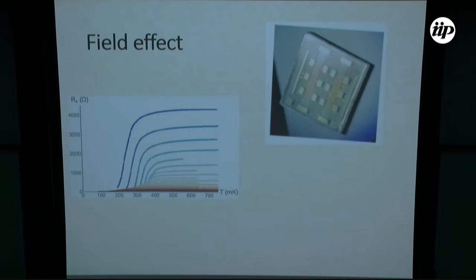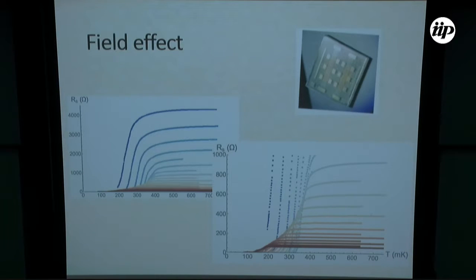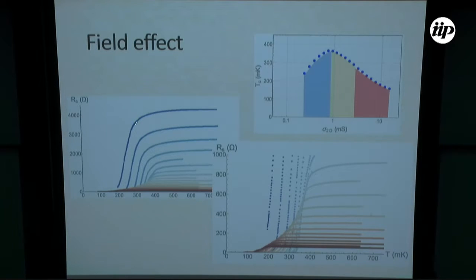We measure the superconducting transition. Here you see it as a function of gate voltage, and the color code is: the blue transitions are for the underdoped region, the yellow ones are for the optimally doped region, and the red one for the overdoped region. So depletion and then accumulation state, the two extremes.